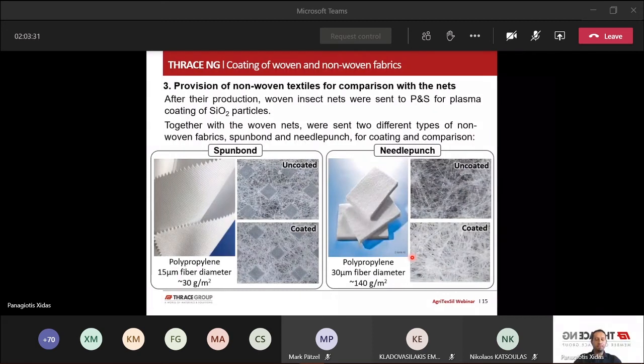In task number three, together with the woven nets that we sent to P&S, we sent also two non-woven samples, non-woven fabrics, spunbond and needle punch for coating and for comparison. On the left side, you can see how a spunbond fabric looks like and how is the fabric's structure uncoated and coated with SiO2 particles. On the right side, you can see how a needle punch fabric looks like and its structure uncoated and coated. You can see how big is the difference between uncoated and coated fabrics.